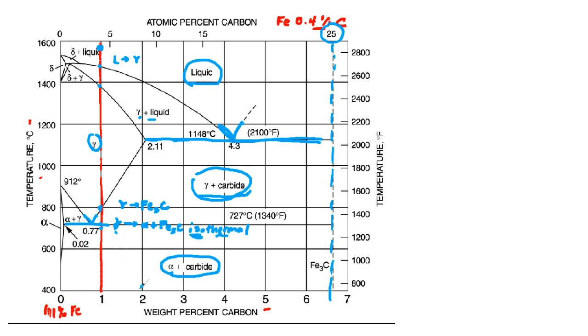Okay, what the heck did I mean by that? Okay then, let's talk about that. Let's look at this valley here, and then where does it extend? It touches this alpha phase. It touches the gamma phase. What is touching this line? The gamma phase bounds this line and touches right at this V. The alpha phase touches here, and the Fe3C phase touches there. So this actually reveals one of the secrets of the phase diagram, and that is when you're in a two-phase or a three-phase situation, the places where an isothermal line touches a single phase will tell you the composition of that equilibrium phase.